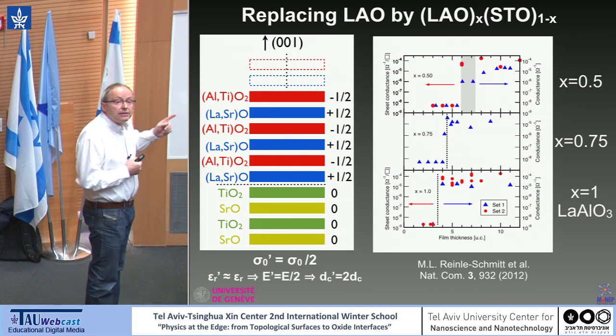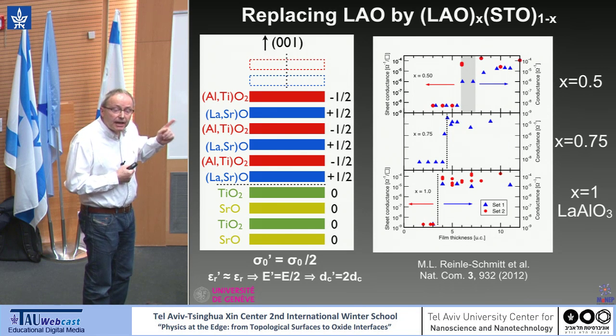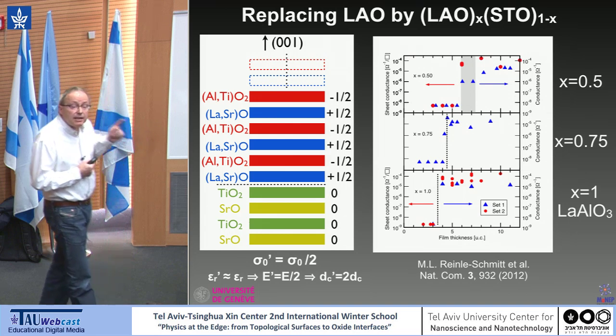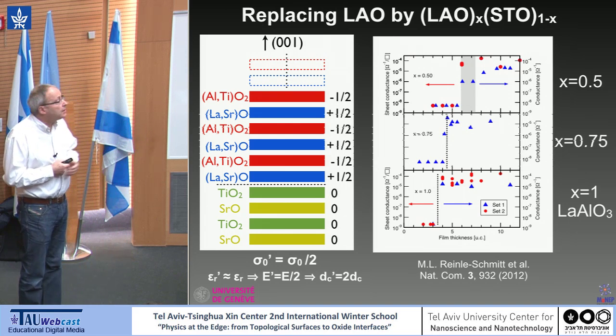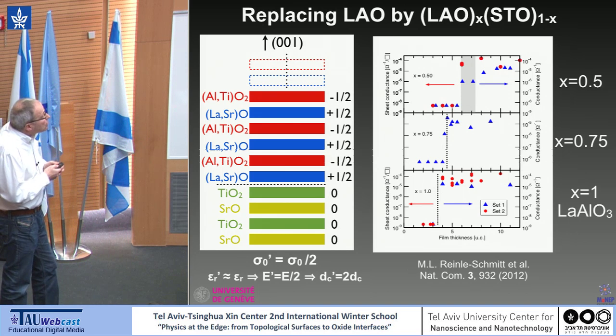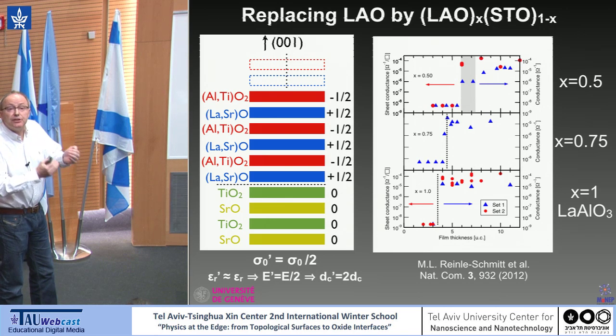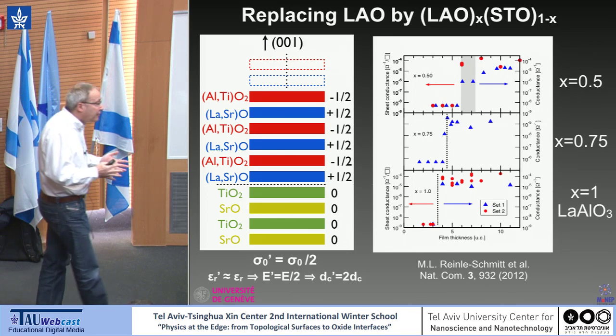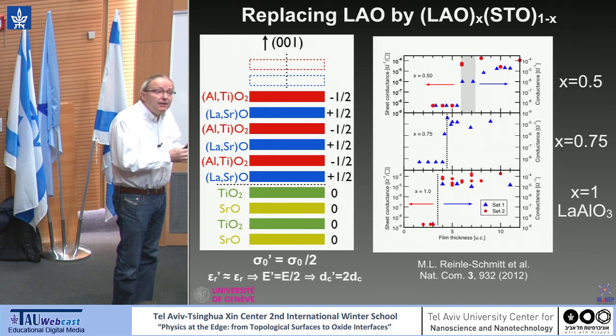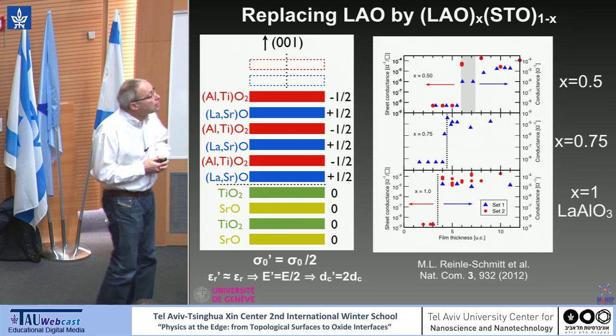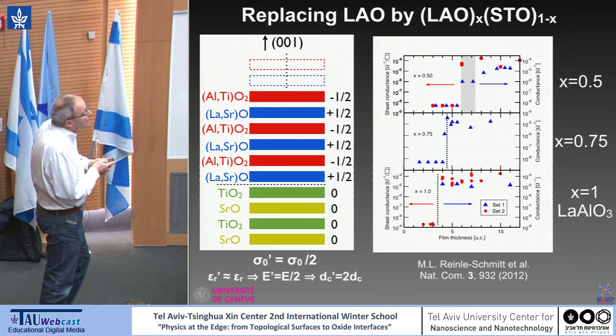Now, it turns out that in this alloy, the dielectric constant is the same as the one of lanthanum aluminate, about 23. And so the only thing which is changing here is the electric field, which decreases by a factor of 2. But now if you think about it, if the electric field is decreasing by a factor of 2, then the critical thickness should double. And this is indeed what we see.